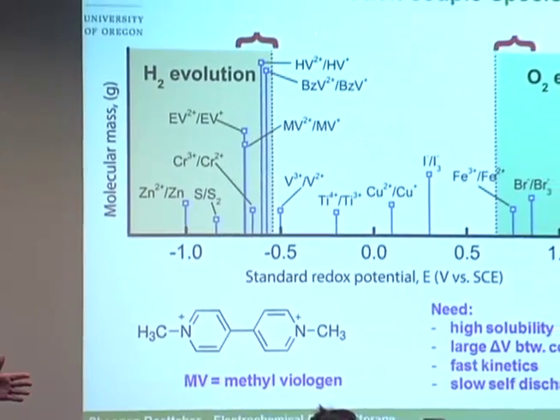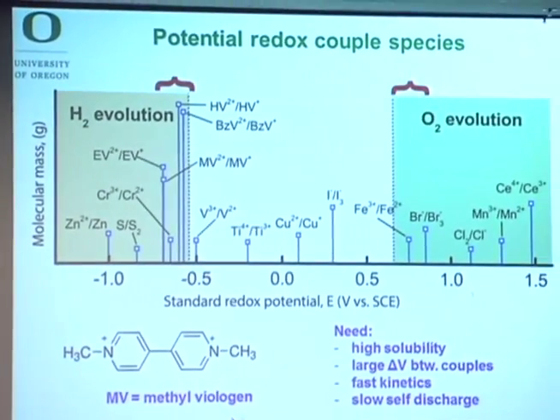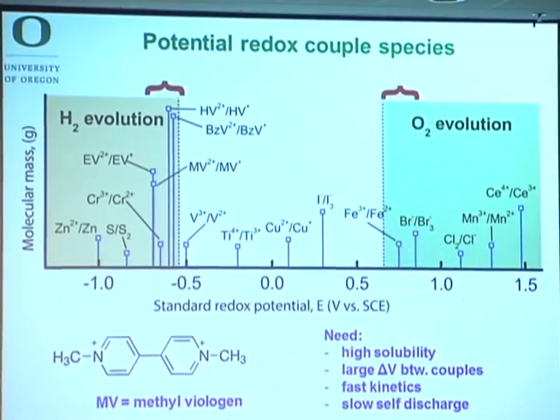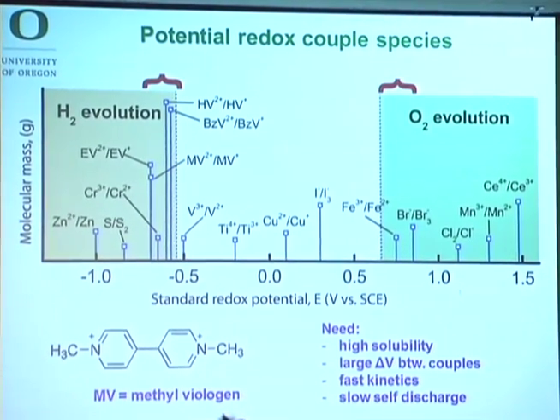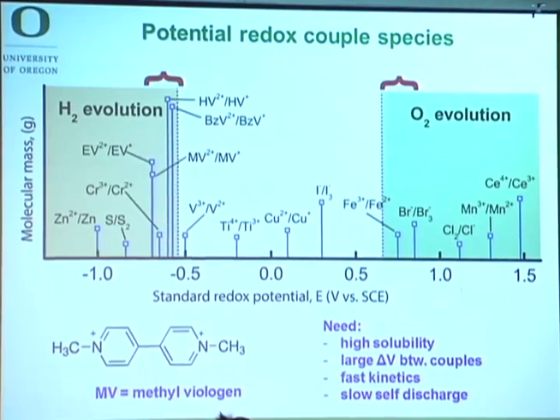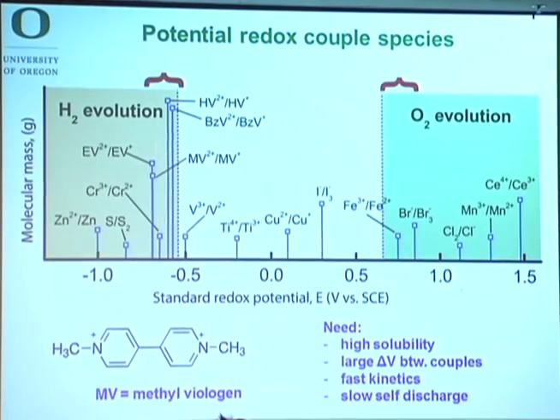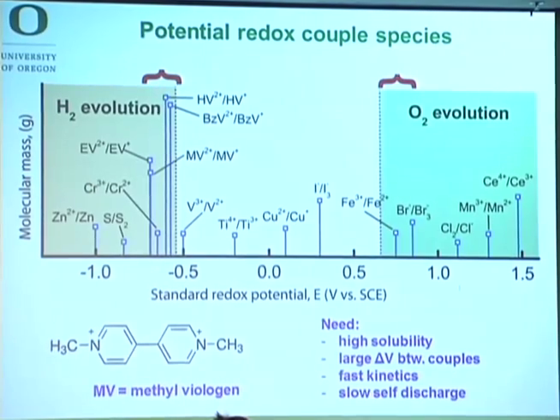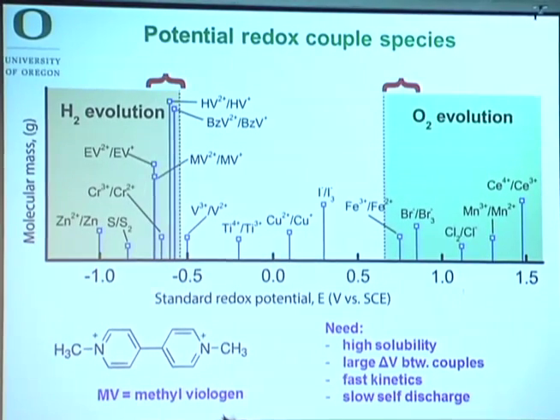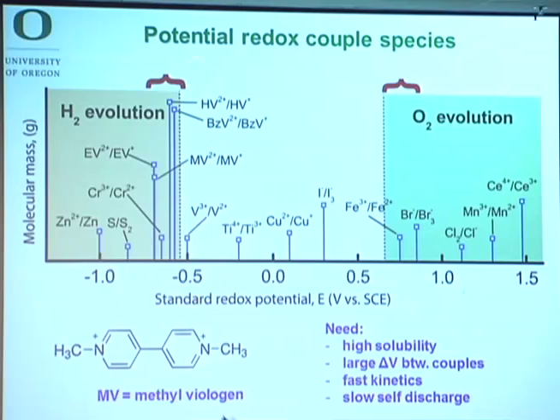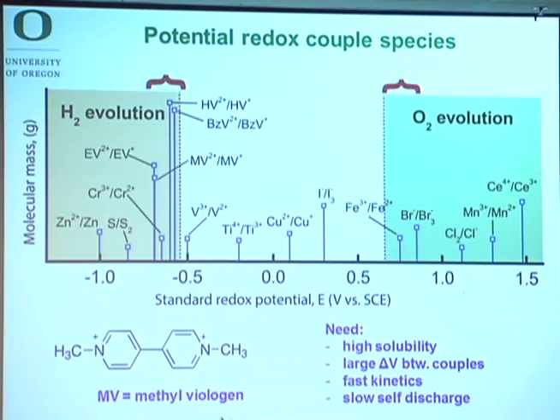So here are a number of redox couples we considered. In the white here, this is the area where water is stable. If you have an electrode in this potential region, you won't make oxygen or hydrogen. If you go outside this potential region, you start running the risk of evolving oxygen or hydrogen. And so what you want is a redox couple on the cathodic side that's near or right beyond the stability window of the electrolyte, so you can store a significant voltage when you drive a redox reaction.